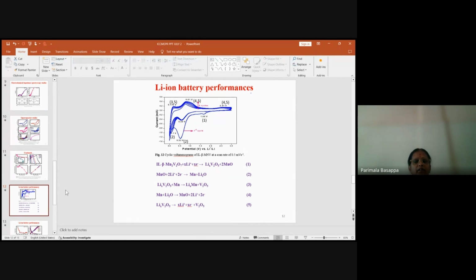So you can see here that this is a delithiation peak and this is the lithiation peak. So this is the first cycle. You can see there is a small peak at about 1.66 volt and another one at about 0.53 volt. This 1.66 volt peak disappears at the second cycle in the cathodic, or you can say lithiation, because this suggests that, according to equation 1, an irreversible reaction was involved in the initial lithium process.